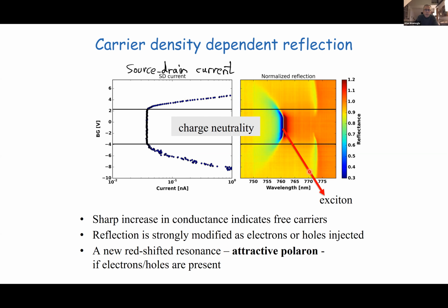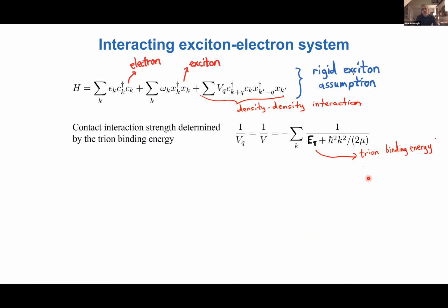These peaks, or the spectra in general, we can understand essentially as Fermi polarons or exciton polarons, and I'll try to describe how we can think of these in the simplest way. Excitons and electrons are interacting particles. I will regard excitons as rigid particles, such that the presence of electrons does not really change the exciton confinement and the size of the exciton. This is an assumption, and it's a reasonably good assumption for densities up to 10 to the 12.